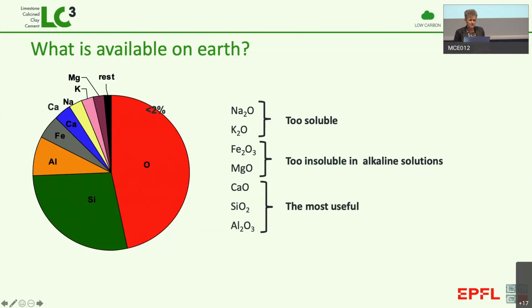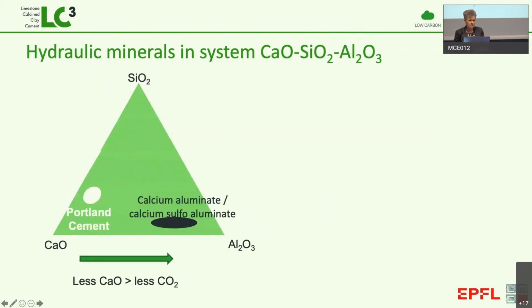And we've been studying this system of 3 oxides for well over 100 years now. We know everything about it. We know all the phases that form. And we basically have 2 areas in this diagram of combinations between silicon dioxide, calcium oxide, and aluminum oxide, where we have cements, these materials that dissolve and then form these new hydrates. And we have this composition over here, which is what we call Portland cement, but it's basically made up of calcium silicates. And we also have this composition over here, which is where we find calcium aluminates and calcium sulfoaluminates.